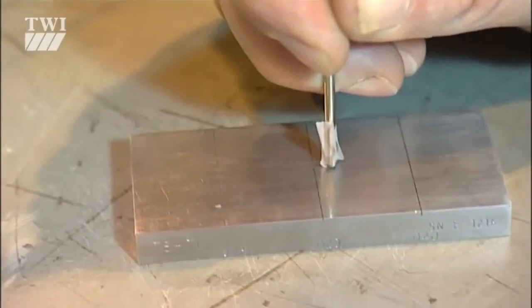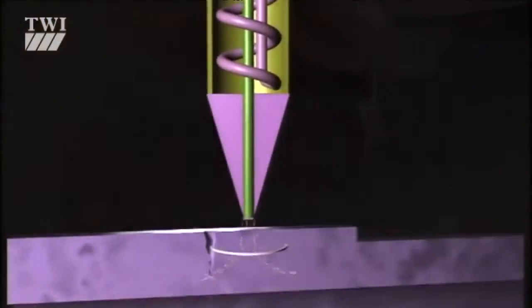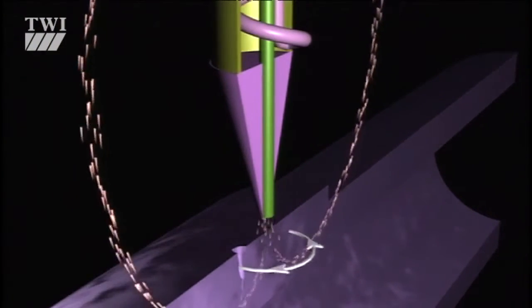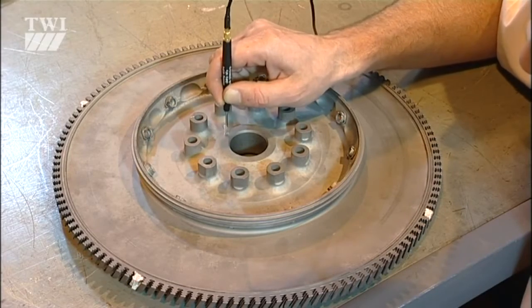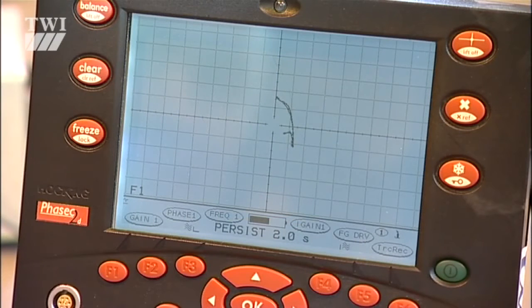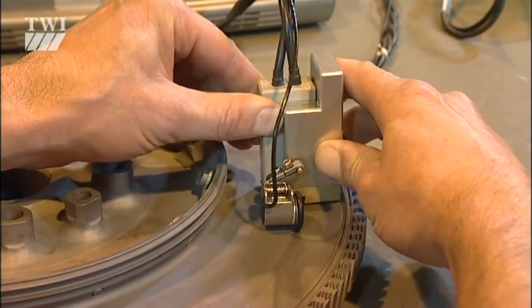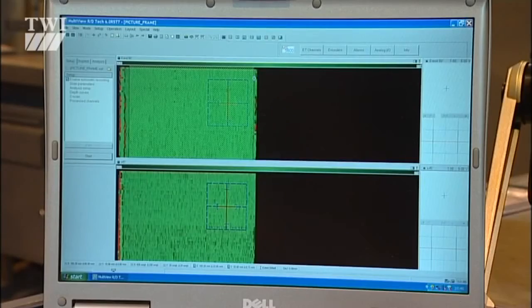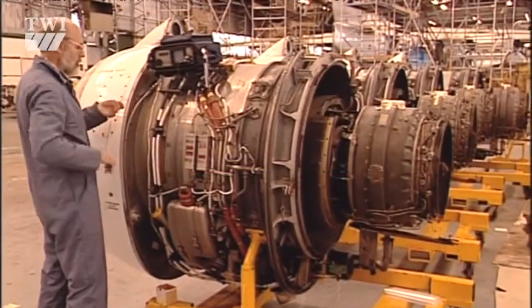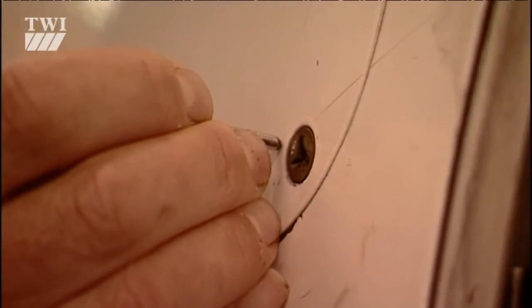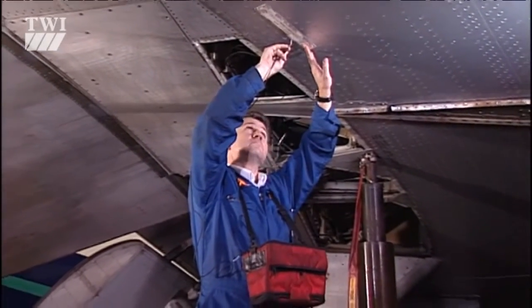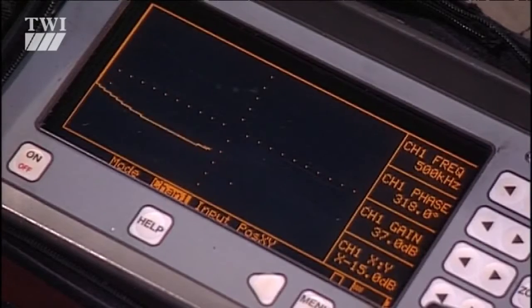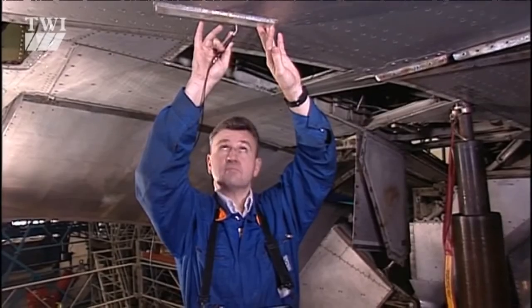In standard eddy current testing, a circular coil carrying an alternating current is placed close to an electrically conductive specimen. The alternating current generates a changing magnetic field which interacts with the test object and induces eddy currents. Standard eddy current testing is essentially a near-surface technique, useful for detecting surface-breaking or near-surface cracking and variations in material composition. Eddy current methods are used for surface inspection of both non-ferritic and ferritic materials. Eddy current penetration is deeper on non-ferritic materials, so it's also used for special applications with thin components, such as the inspection of multiple-layer airframe components for cracking or corrosion thinning.